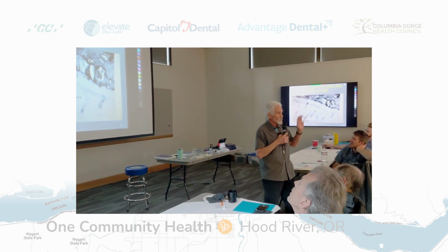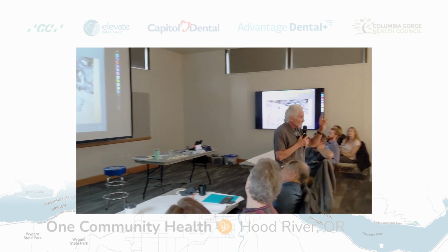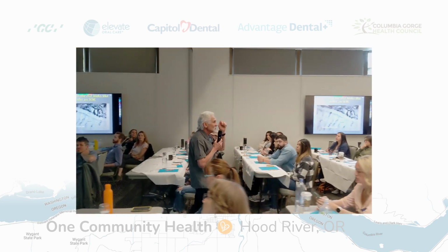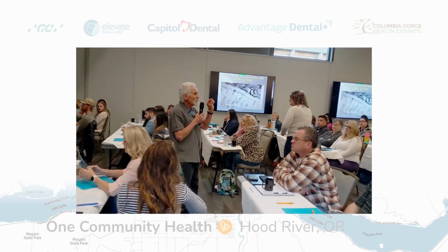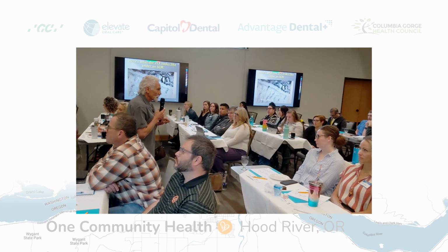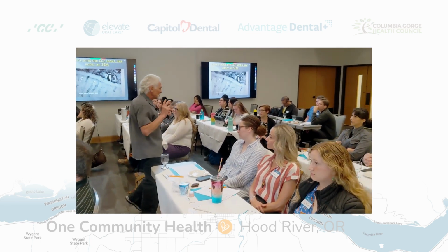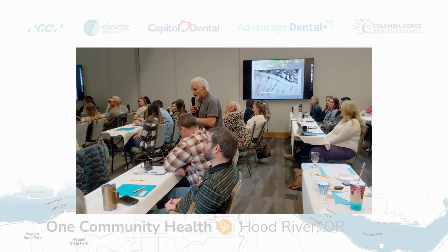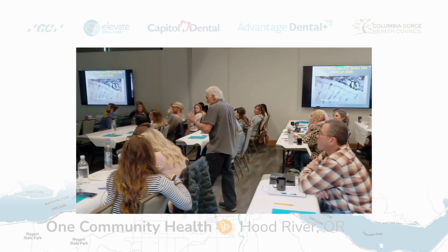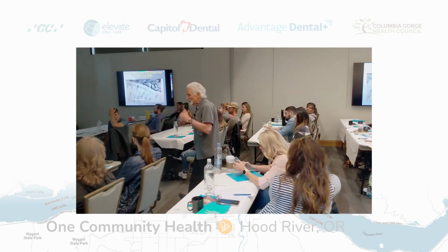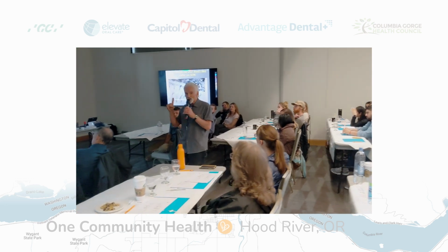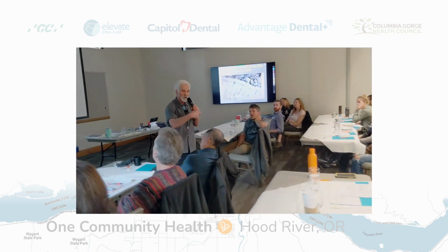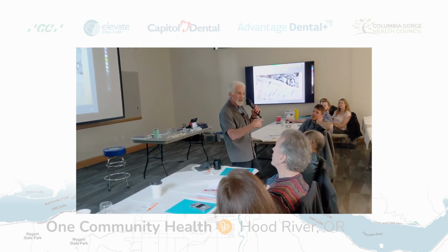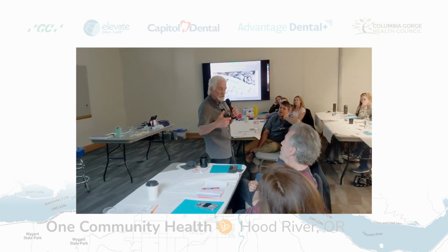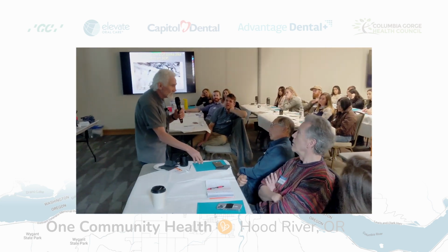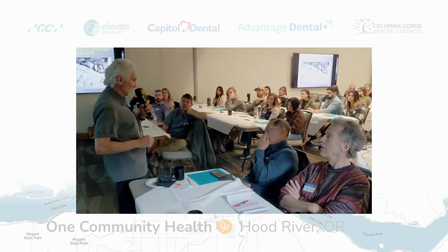This zone happens with resin-modified glass ionomer. The difference is, with a resin-modified glass ionomer, if you don't light cure that dual cure stuff, it leaves unpolymerized resin on the surface. Test it. Take some Fuji 2, put it on a mixing pad, and let it cure. Give it 20 minutes, half hour. Go treat a patient, come back in 2 hours. You feel that with a fresh gloved finger, and you're going to feel that greasy, unpolymerized layer. That's weakness. Now take another dab of Fuji 2, put it on the mixing pad, set the light to it, take a new glove, feel it, and you don't have the unpolymerized resin.